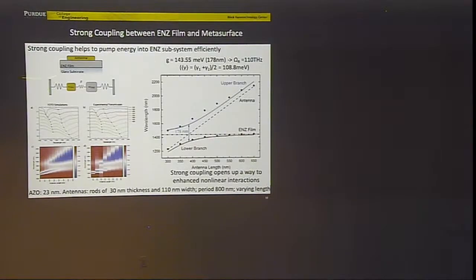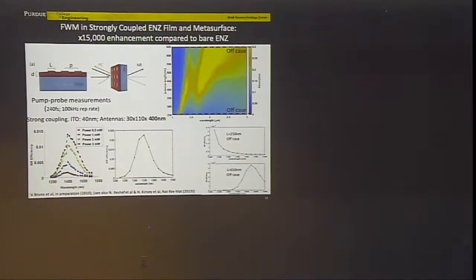The problem could be described by two coupled oscillators: one oscillator representing the ENZ mode, another representing the resonant frequency of my antennas. This is a very simple model which fits the experimental data nicely. And you have this typical splitting, which is a feature of coupling. This splitting is actually larger than the decay constant for both the antennas and the ENZ mode, meaning that this is strong coupling. What we obtain is a 15,000 enhancement of nonlinear response compared to bare ENZ material. So ENZ material is already great, but it's hard to get energy inside. By combining it with a metasurface, we have a 15,000 further increase in enhancement of the nonlinear response.